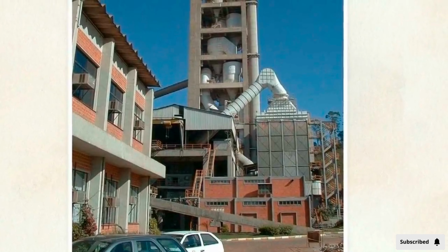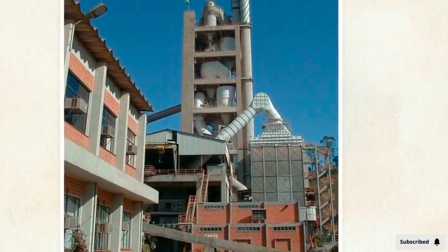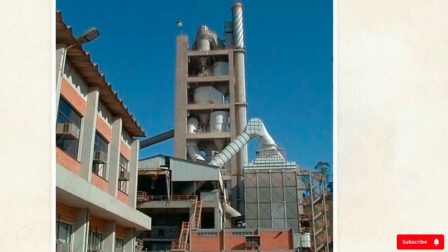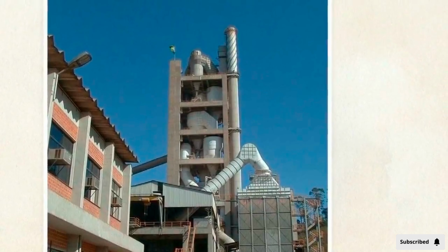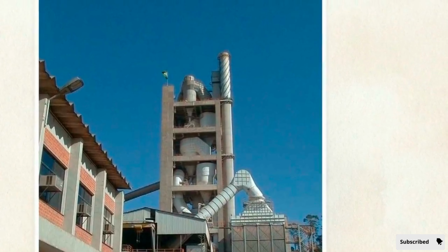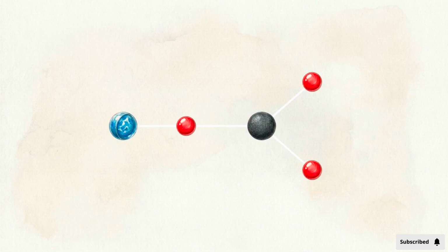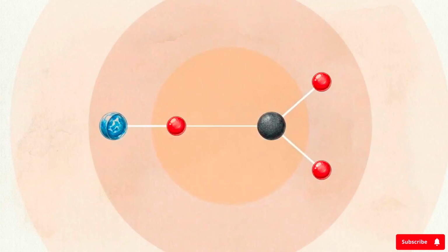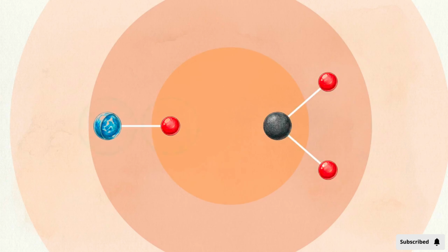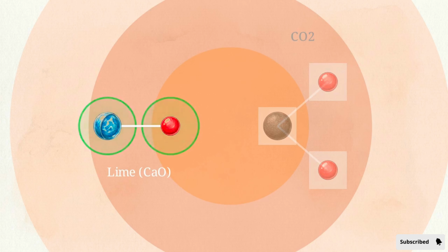This raw meal is fed into a precalciner. Inside these towering structures, the powder is suspended in a rising column of high-temperature gas. At approximately 900 degrees Celsius, a reaction called calcination occurs. The heat causes the calcium carbonate molecules to fracture. They split into two parts: lime, or CaO, which we need, and carbon dioxide.